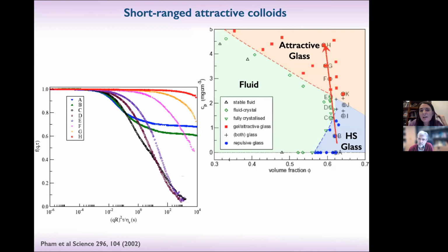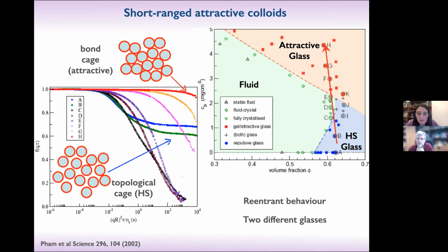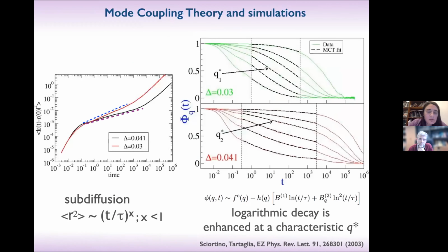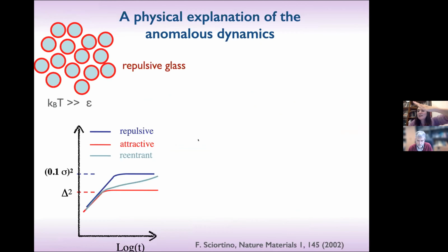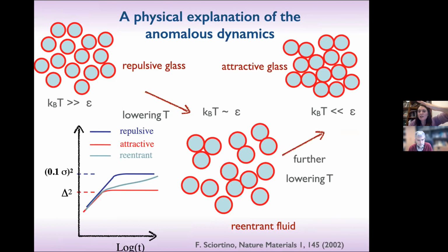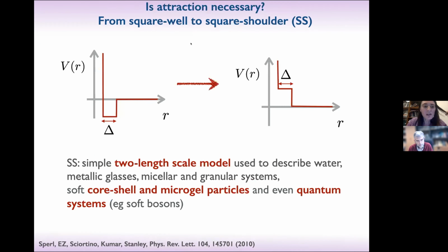I agree with you. I think that if you go to very, very large packing fraction of the large spheres, they become effectively immobile. But then, when you go there, you first meet these other mechanisms. So there is this range in between where you are in the middle, let's say. But I agree with you. At very, very large packing fraction, you will eventually arrest. Although, let me tell you that if you remember my slide, we were at packing fraction 62% of the large spheres.